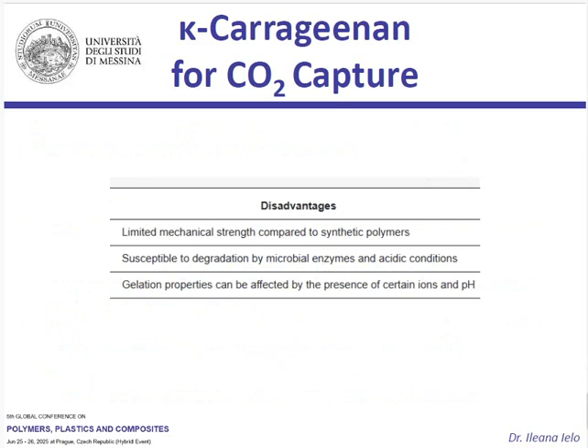However, it's also important to consider, in this case as well, a disadvantage: it has limited mechanical strength, which might impact its long-term stability in certain applications. It can also be susceptible to enzymatic degradation, and its gelation conditions are quite sensitive, depending not only on pH, but also on the ionic strength of the solution.